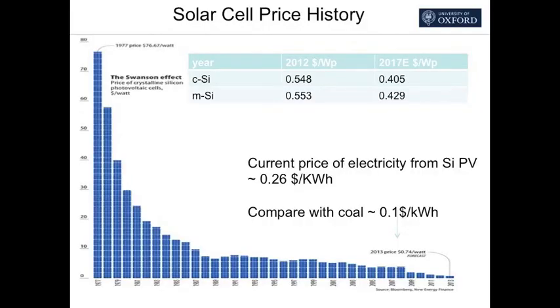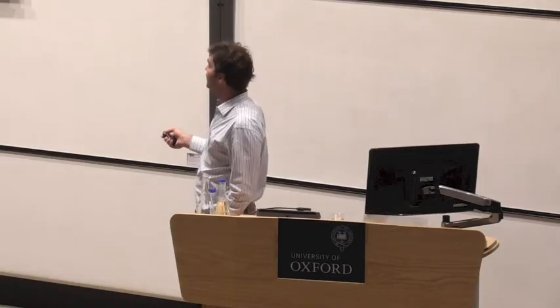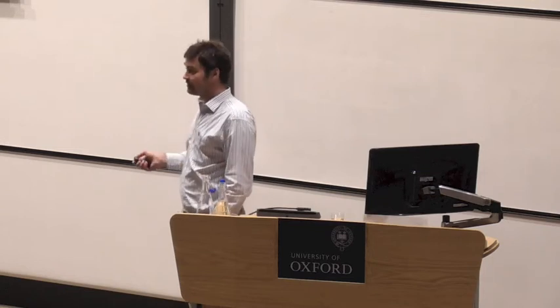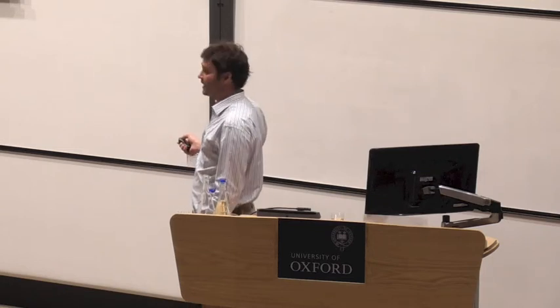And the other question is, how has it been achieved so far? Well, that's quite simple by looking at the historic cost of silicon PV. In 1977, it was something like $76 dollars per watt peak, and that's dropped down to about 74 cents per watt peak. So a 100-fold reduction over this time period, and this isn't set to plateau yet.